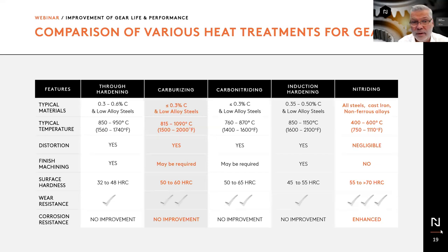Of course, here you have a temperature difference, where carburizing is performed above transformation temperature, above 800 degrees Celsius, above 1500 degrees Fahrenheit, whereas nitriding typically will be done at temperatures in the range of 400 to 600 degrees Celsius, depending on the core hardness and allowable maximum temperature in order to prevent a second temper, which is roughly 750 to 1100 degrees Fahrenheit.